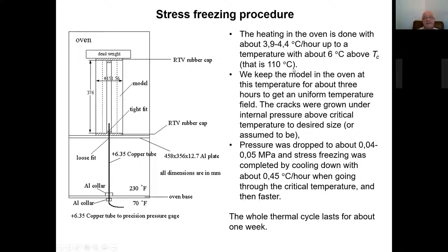So we went up to 110 Celsius. And then you keep the model for some hours. Of course, you have to look carefully at what is going on with the crack, how it grows due to the internal pressure. So essentially, the crack is naturally grown in this model, and then you cool back with a very, very small temperature gradient, 0.45 degrees per hour, where we essentially dropped the temperature to go through the so-called critical temperature and freeze the stresses. So one of these thermal cycles was taking about 1 week.